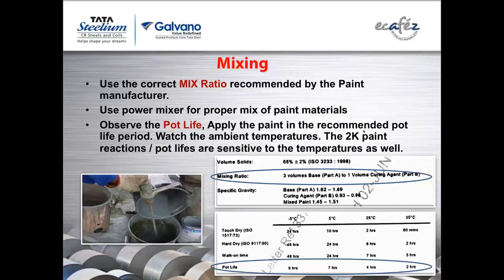If there is a higher amount of hardener, the film is going to be brittle. If it is still higher, it may crack also. If it is on the lower side, usually that film will be soft and naturally you will have a lot of scratches. If it is still lower, the film will come off, adhesion will be bad.